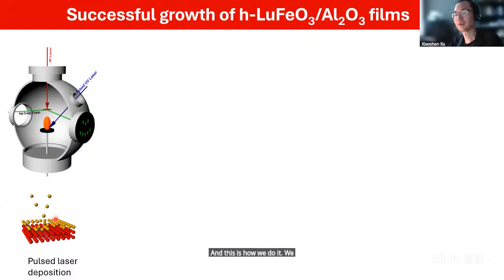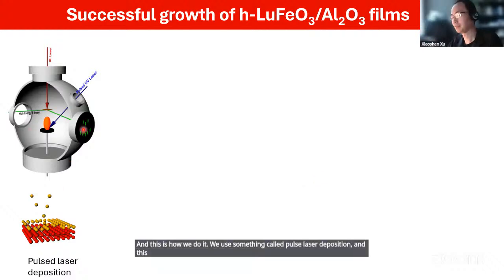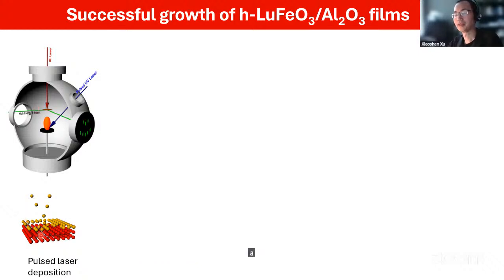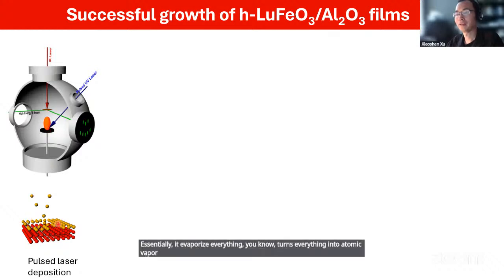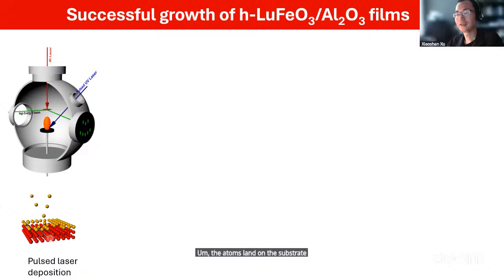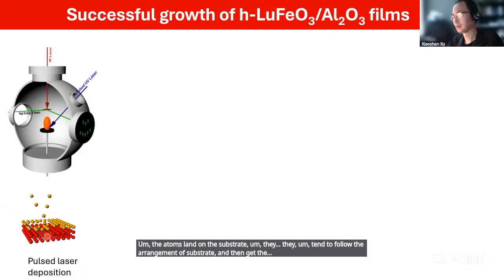We use something called pulsed laser deposition, and this is a diagram. The detail doesn't matter. The idea is you start with a template with the symmetry you want. We call it the crystalline substrate, and you spray atoms on it, right? The atoms come from the pulsed laser. This laser pulse is extremely powerful, so it essentially evaporates everything, turns everything into atomic vapor, and then the atoms land on the substrate. They tend to follow the arrangement of the substrate and then get the hexagonal arrangement.